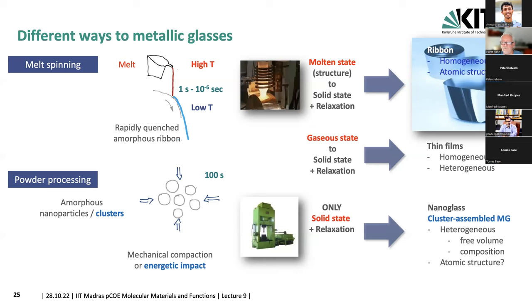Not only is the structure different, but also the properties are different. Mechanically, they become ductile instead of showing brittle fracture like the rapidly quenched glass. We also have seen that there are magnetic properties which have changed drastically if we do this compaction process.